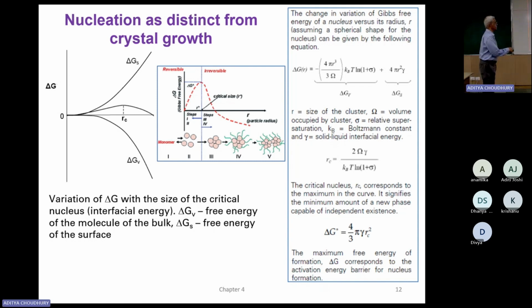When it started growing, you can arrest it at any time. Arrest it and get new nanocrystals. Because it started forming, it's stabilized, and you can stop it. So this is what is happening. So it's called a critical radius that it has to reach. So then you started getting it. After that, it doesn't go back. But there will be so many nucleus formations inside, and once formed, so many nuclei started growing outside. So these are all happening in the supersaturation.